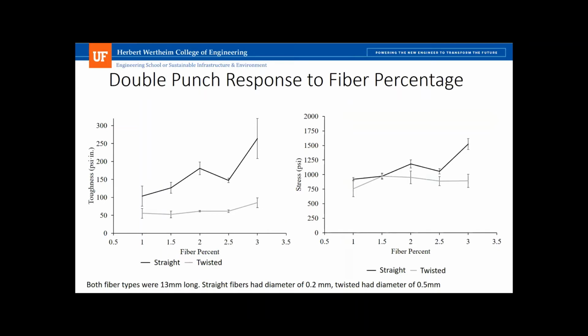So we looked at different fiber percentages for ultra high performance concrete to look at how they affected the results in this double punch test. And we found that 2 different types of fibers, that you get very different results if you just look at the stress, basically the strength or maximum strength of your material. And part of this is because you can get a very high strength, failure strength, just from the first cracking load, basically the strength of your cementitious paste system, even without the fibers. You can get a very high load, but then it cracks and you get no strength, no residual strength after that. And that's why you really need a measure of toughness or ductility. And so with our fibers that were not giving us a ductile response, the double punch test was able to nicely pick that up and picked up the toughness with our straight fibers pretty well.